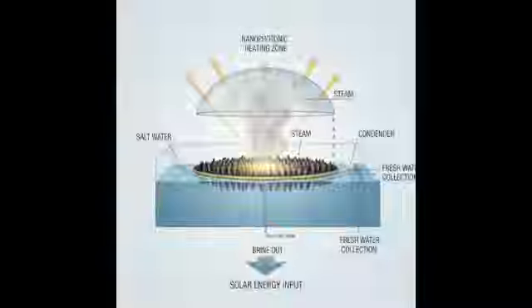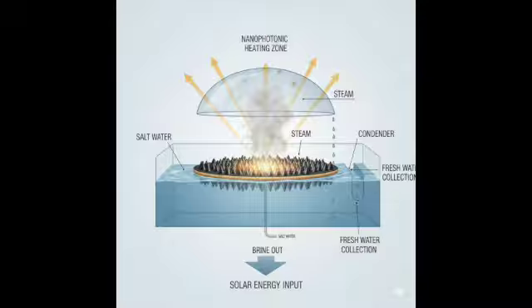Besides solar absorption, are other localized heating methods being looked at? Yes, researchers are exploring things like joule heating, passing an electrical current through a conductive layer on the membrane, or induction heating, using magnetic fields to heat embedded nanoparticles. But solar photothermal is the main focus for SPMD due to the free energy source.